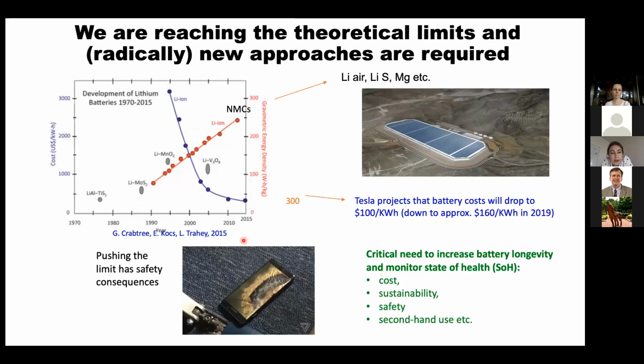But I think that one of the points that is now becoming apparent is that we're really quite close to the theoretical limits of the current technologies. So if you look at this nice graph produced by George Crabtree and co-workers a few years ago now, they were able to show that the energy density, or in this case, the gravimetric energy density, has increased by about a factor of 3, going from some of the early systems through to the NMCs. If we really want a step change in energy density, we're going to have to think about new technologies, be it lithium air or lithium sulfur, possibly even magnesium.